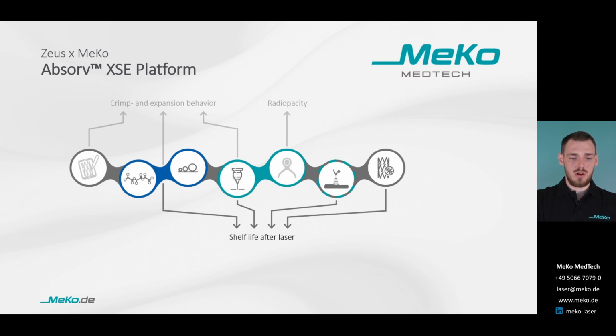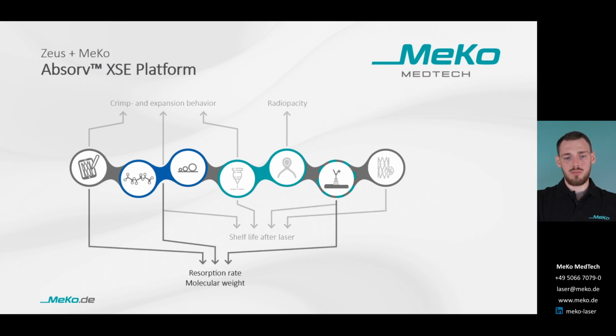Finally, we have the resorption rate, which is probably one of the most important features for a BRS. This is for sure determined by the chosen material, but also influenced by the design itself. In general, the bigger the cross-sectional area of a single strut is, the longer it takes. And besides the design and the material, the resorption rate can be slightly influenced by the coating. In the end, of course, it also depends heavily on where the device is implanted.